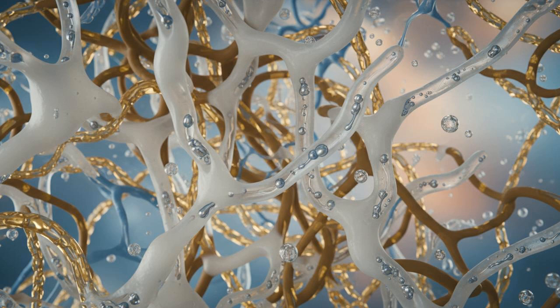But what about the electrodes? Even the best conductive polymers often have too high a resistance. The solution is liquid metal, specifically eutectic gallium indium, or EGaIn. This is a metal alloy that is liquid at room temperature. It conducts electricity like a copper wire but flows like water. By encapsulating microchannels of liquid metal within a rubber substrate, engineers can create electrodes that remain perfectly conductive, even when stretched to 300% of their original length.